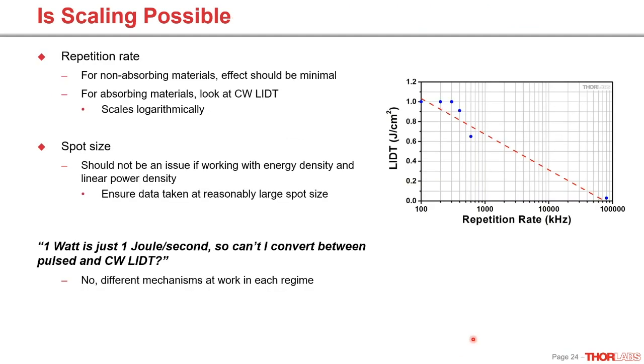As far as repetition rate, this should have minimal effects for non-absorbing materials. For absorbing materials, you're also going to want to look at the CW damage threshold for the average power. And for some absorbing materials, you will see that the damage threshold will scale logarithmically with repetition rate, and that can be seen in this graph over here, which is from some data in the literature.